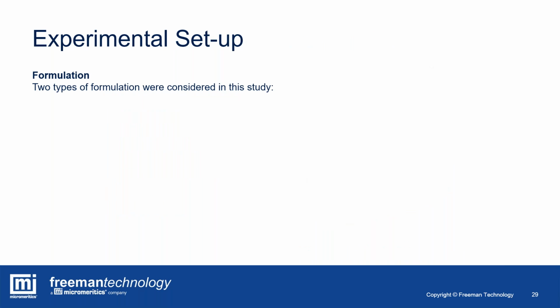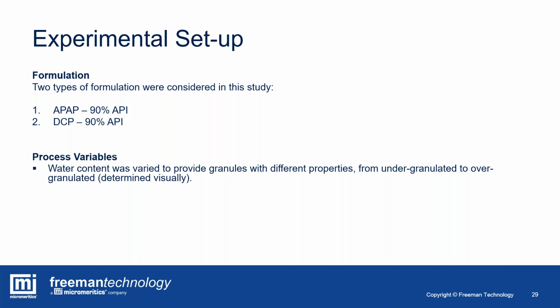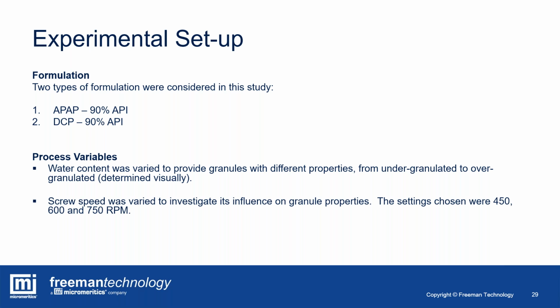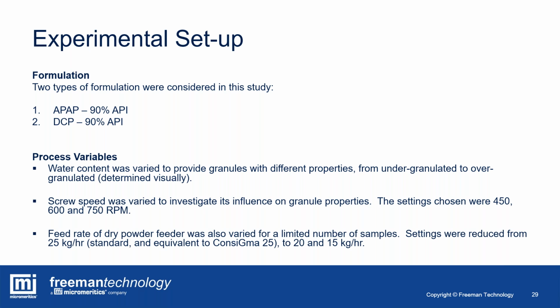So in terms of the experimental plan we had with the collaboration we did with GEA, we took two formulations, pretty straightforward. One was an acetaminophen, an APAP or paracetamol with a 90% drug loading. The other one was dicalcium phosphate, again, high drug loading. We wanted to change process variables by varying the amount of water required to provide granules that had different properties, of course, from undergranulated to overgranulated, and that was determined visually. We wanted to manipulate the screw speeds, so we chose 3 different screw speeds of 450, 600, and 750 RPM, and we wanted to change the feed rate of the dry powder feeder into the screw itself, and we deviated from the standard 25 kilograms per hour to a 20 and a 15.